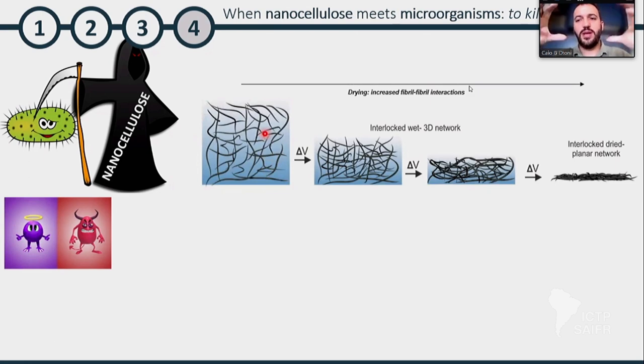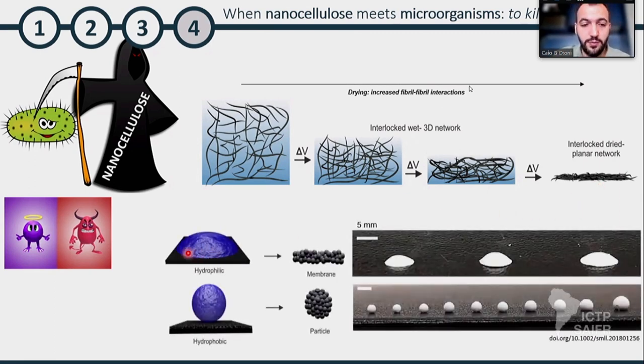So you have a suspension, it's highly hydrated, it's viscous because I'm talking about nanofibrils that entangle, right? And they imprison water. And as we dry, what we do, we pack the chains, right? So we increase gradually the solid content and the number of contacts between the fibrils until I have something that is interlocked. Sometimes I don't even have to chemically crosslink because this interlocking, this entanglement is enough to give me robustness and resilience even in aqueous medium, right? So depending on the way we do it, if we go for a hydrophilic substrate, we have what we call a film, a flat film, because the solution, usually water, will wet, spread, and dry as a film.